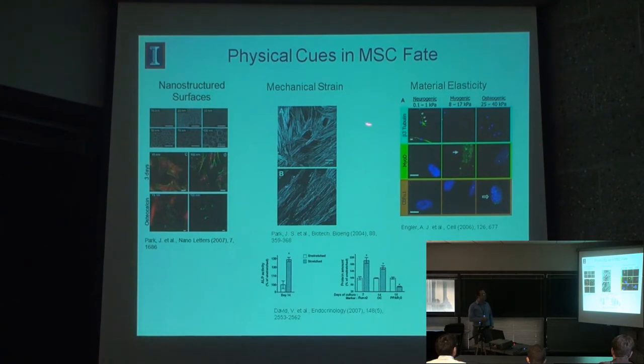And they made a really startling observation, which I think makes a lot of sense, in that as you change the mechanical properties of the matrix on which these stem cells are sitting, you change the way that they differentiate. So here you see cells on this soft matrix are expressing markers associated with neurons. They're developing neuronal-like phenotypes, too, by extending out processes. On the intermediate stiffness gels, you see muscle markers. And finally, on the stiff gels, where the cells are very spread, they have high cytoskeletal tension again, and they start expressing bone markers.